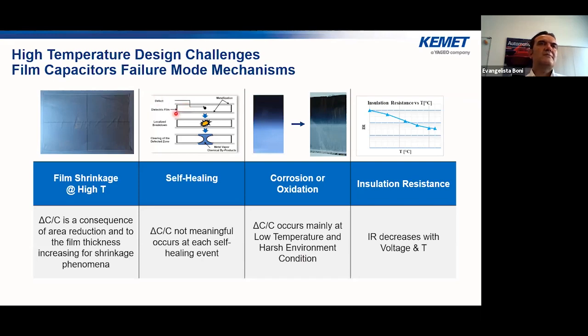Here we can see the main four failure mechanisms. We can start from the film shrinkage. The film is on the left. The film is plastic, and when plastic is submitted to temperature, it shrinks. The plastic at the beginning of this process is stretched in the transversal and longitudinal directions.